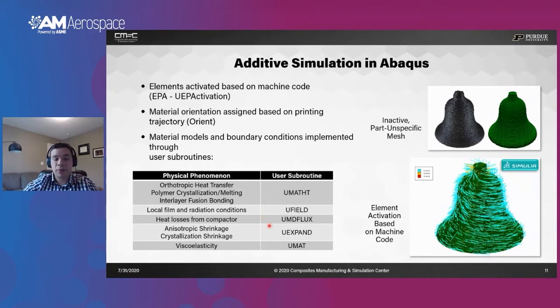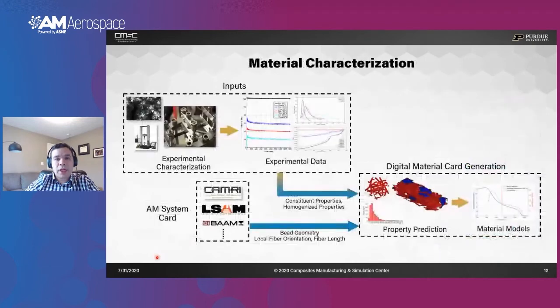The heat losses removed by a compactor, in the case of using either a roller or a tamper for consolidating the printing material, there is heat removed by the action of the compaction mechanism, so we can account for that. But at the same time, we also capture the anisotropy in the shrinkage and in the viscoelastic behavior of the printed material. So this is important in order to capture the physics that underlie this manufacturing process.